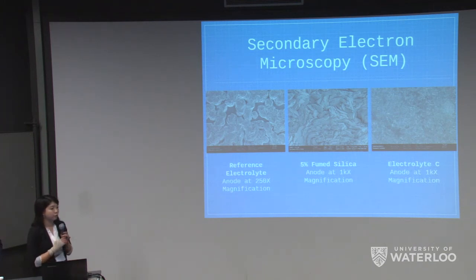If you take a look at the 5% fumed silica anode at 1,000 times magnification, you can see that the type of growth is actually flake-like. With this, it causes a more amorphous growth and requires more deposition for the electrode to be able to create a short circuit.